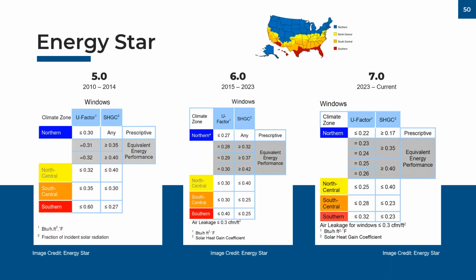Now, if we were to think about various standards for high performance, what do we consider as high performance? Energy Star has always been one indicator of higher performance, meaning higher than code anyway. And we don't have to look too far back in history to see the advancement of Energy Star compliance in windows. If we look first at the solar heat gain coefficient, you do see some evolution through these different versions. But the bigger factor here is the U factors have really ratcheted up. Going back to as recently as 10 years ago, Energy Star was noted to be as high as 0.30, which we saw in the earlier slides.